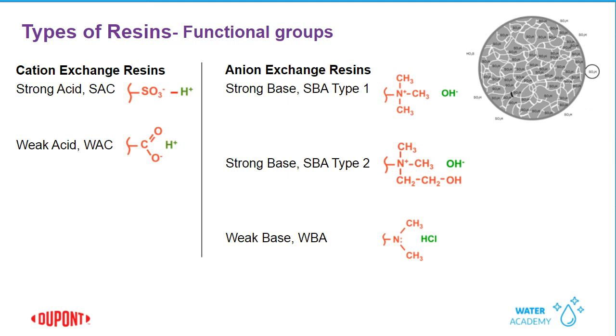The third anion resin that I have listed is a weak base anion resin. You'll notice that there's no positive charge on this nitrogen. This is a tertiary amine, and this resin isn't your typical ion exchanger. I would consider it more of an acid adsorber. Weak base anion resins can be used in conjunction with strong base anion resins to do two things. One, to provide chemical efficiency, just as in the cation resins. But also, weak base anion resins can remove organics and elute them very well compared to a strong base anion resin. So it can provide protection from organic fouling for the strong base resin.